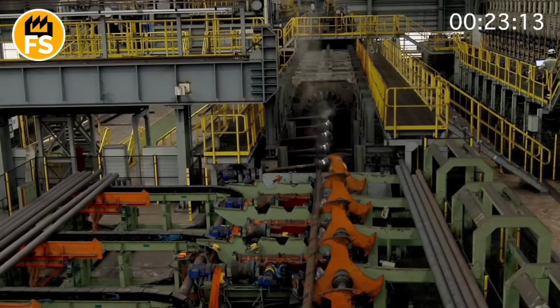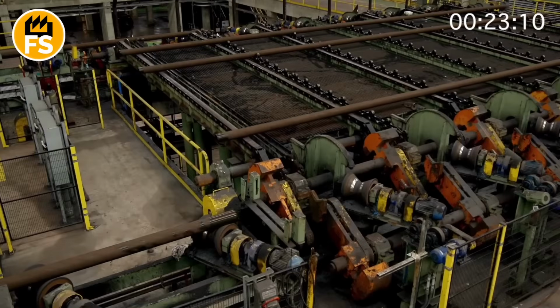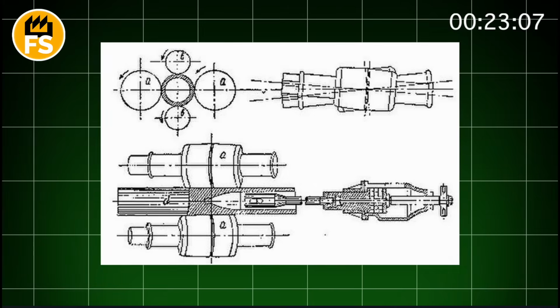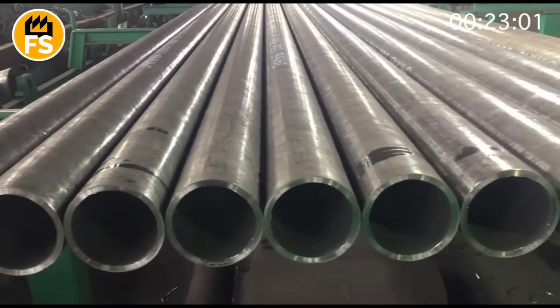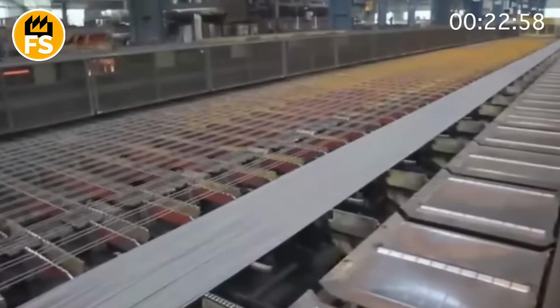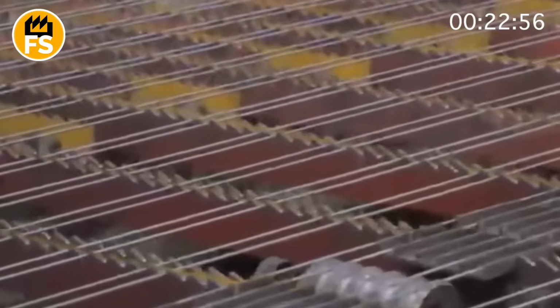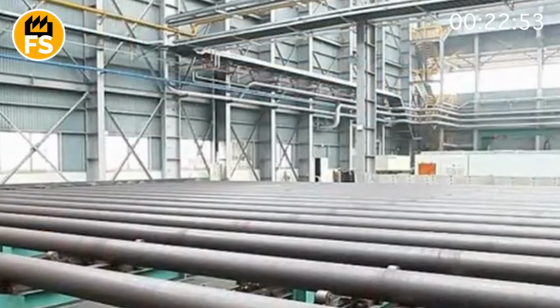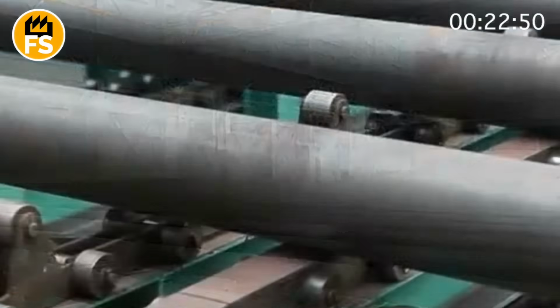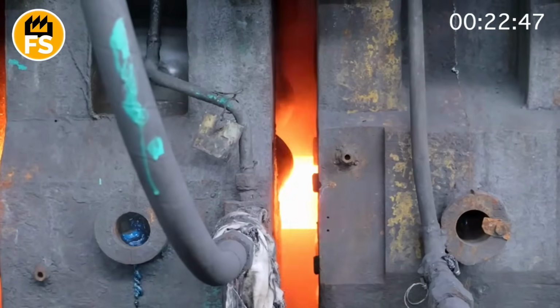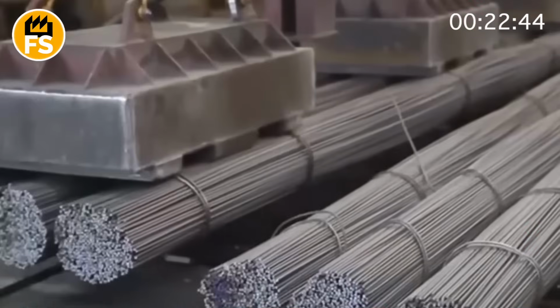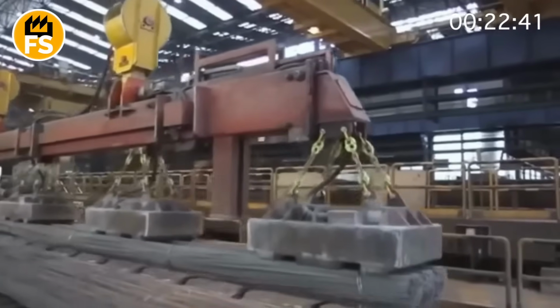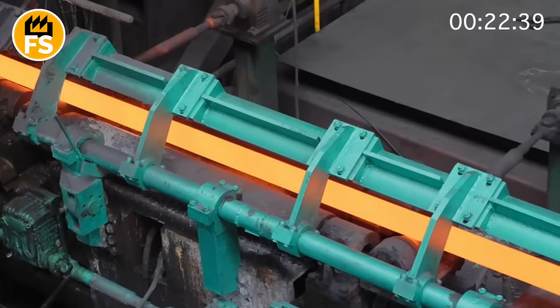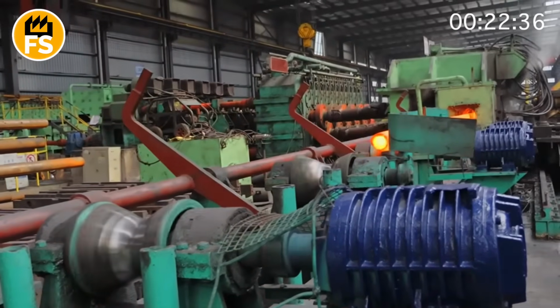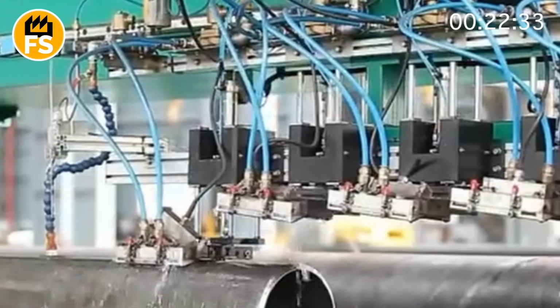This process is called the Mannesmann method, named after the German engineers who invented it in 1885. After the initial piercing, the resulting rough pipe is called a hollow shell or bloom. The wall thickness of the shell is approximately 2 inches. It still has uneven walls and may contain small defects, so the next stage is rolling and calibration, where the pipe is stretched, straightened, and brought to the required dimensions and wall thickness. The red-hot steel billet enters under giant rolls 5 feet in diameter. Under tremendous pressure, it's drawn out into a slender pipe up to 40 feet long, faster than you can blink.